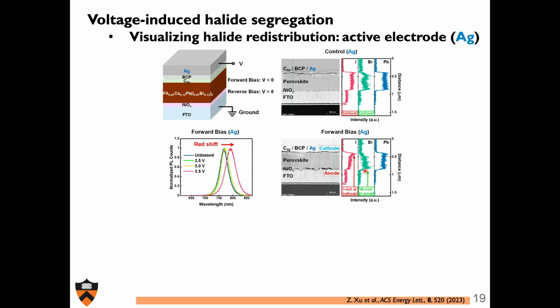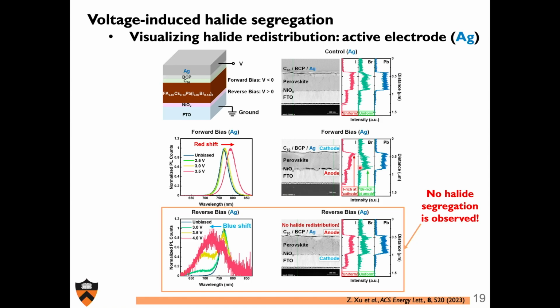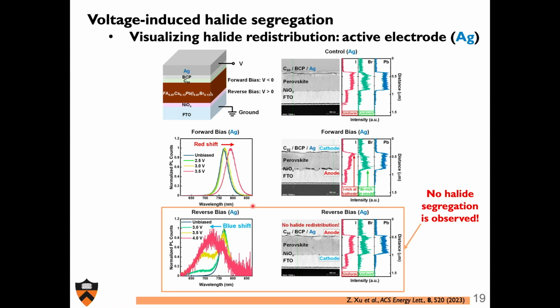But now I reverse bias the situation, and silver is now my anode. So what happens is silver is more easily oxidized than iodide. And so I have effectively interrupted the iodide redox cycle. And if you believe me that iodide oxidation is at the core of halide phase separation and redistribution, then because I've interrupted iodide oxidation, I no longer have halide phase separation. And that's what I see. Iodide and bromide are both well distributed and equal to that of the lead component. And as a consequence, I'm actually bringing silver into this system. So silver is now entering the lattice, because something had to have gotten oxidized. And in this case, it was silver. And does anyone have a guess what got reduced?